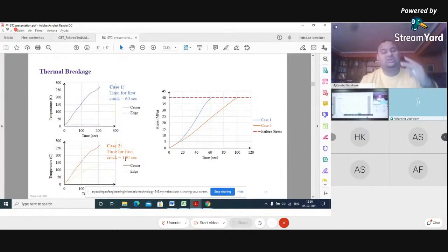So we got two vital points. One was glass does not break due to the temperature, it breaks due to the thermal gradient across the length of the glass. Second, if we restrict the thermal expansion of the glass, it starts breaking. Otherwise, we have time and it will not be breaking soon. So these were the 2 points that we have obtained from our experimentation on the glasses, and we worked on